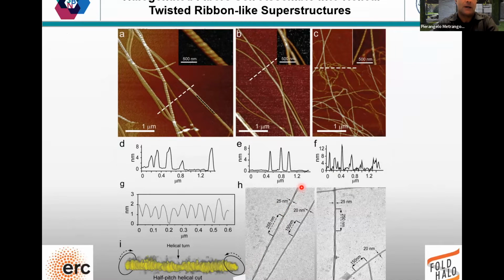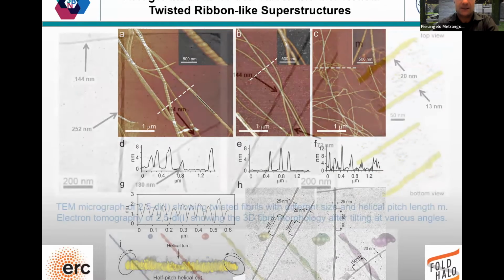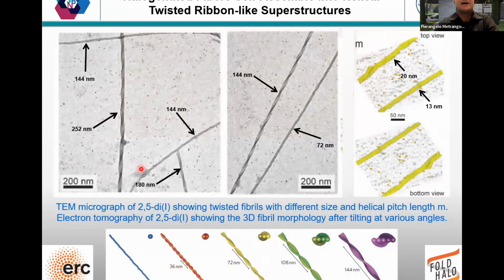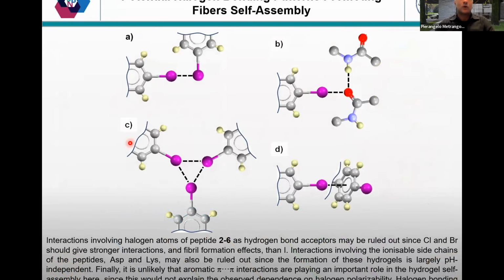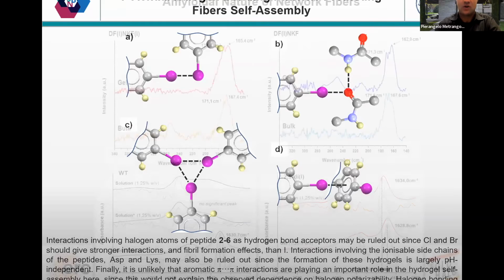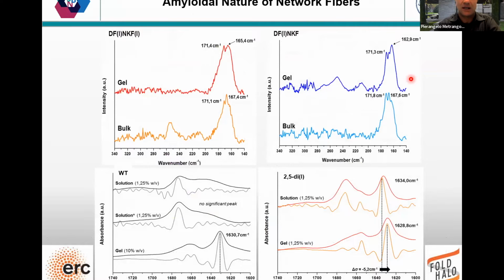a very mature helices, which are quite unusual for such a small pentapeptide. These are microscopy images of the peptides where you can clearly see the very big helices. And obviously we could not get high resolution structures of these fibrils. So there are several possibilities for halogen bonding there. But we believe that the most suitable is this one, because from the spectroscopy, we see the change in the stretching of the carbon-iodine bond in the Raman, coupled with the IR change in the peptide bond. So we believe that this is the kind of interaction occurring and responsible for this improved fibrillation.